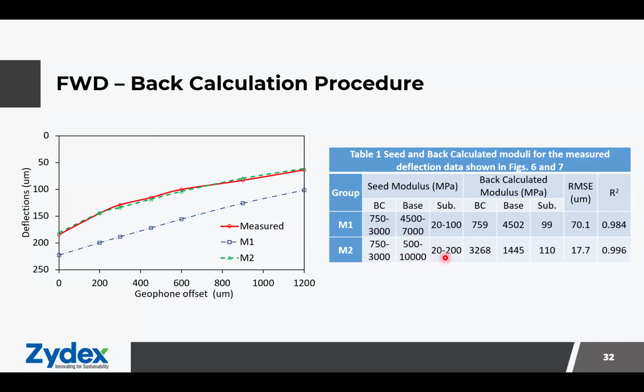For subgrade, we have also given from 20 to 200 MPa modulus. What we get is the back calculated moduli for the BC layer as 3200. For the base, we are getting around 1445 MPa, whereas for the subgrade, we are getting 110 MPa.